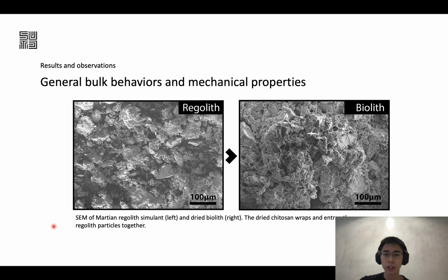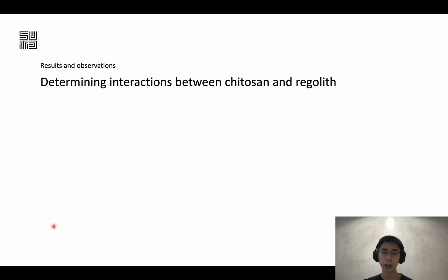From this observation, we went on to investigate whether this interaction between chitosan and the regolith particles is based on a chemical reaction or physical interaction. To do that, we performed two types of tests. One is FTIR, which is Fourier transform infrared spectroscopy, and the other is DSC, which is differential scanning calorimetry. With these two tests, we are trying to compare the absorbance spectra and the heat flow patterns as measured while we increase the temperature. So let me dive a little bit more into the FTIR.